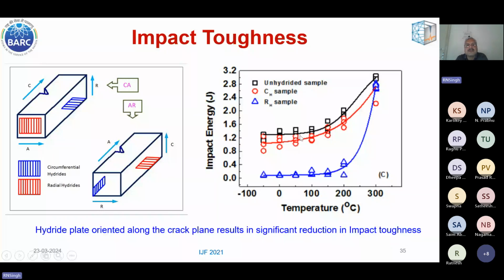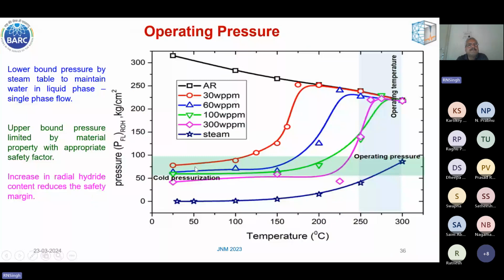Now we determine this fracture toughness parameter, but what do we do with it? So these data are required for safety assessment. Here, there is a parameter called operating pressure. We all know that coolant heavy water is used in pressurized heavy water reactor. And in order to attain higher heat extraction, we want to maintain the heavy water in the liquid phase. For that, we have to pressurize it. So lower bound pressure is decided by the steam table, that you have to keep the water in liquid state. However, upper boundary is provided by the fracture toughness of the material.